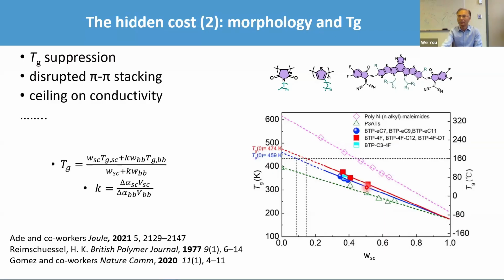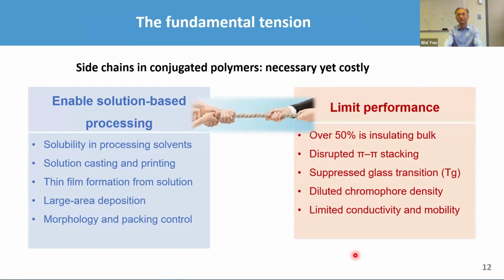That's a lot. Once you add more and more side chain, of course, you essentially end up with the side chain only situation. That's essentially polyethylene or polyalkane, and you end up with a below room temperature Tg. So at the end of the day, you essentially take the weighted distribution of the high Tg of the backbone and the low Tg of the side chain, and you end up with somewhere in here. If you try to make your solar cell or electronic device very thermally resistant, you possibly want to have a high Tg. So that's one of the reasons why we go after side chain cleavable materials.